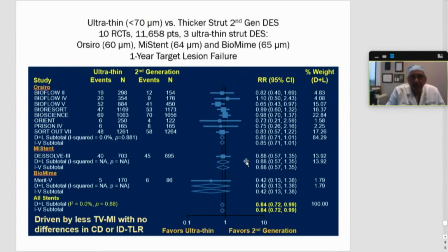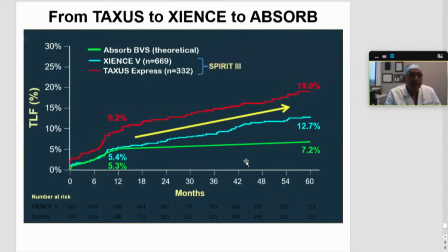But the real advance, to be honest, is probably around ultra thin struts. I mean, we have gone from 140 microns now down to 80s, and now we are going below 70 microns. I think that compared to thicker struts, ultra thin continues to outperform them. I mean, we have many trials, more than 10 RCTs with more than 11,000 patients on ultra thin struts. The one which is available in the US right now is Orsiro, which is only 60 micron thickness. And the TLF rates, as you can see, are definitely comparable, and also lesser than second generation drug-eluting stents. So this is very encouraging news.